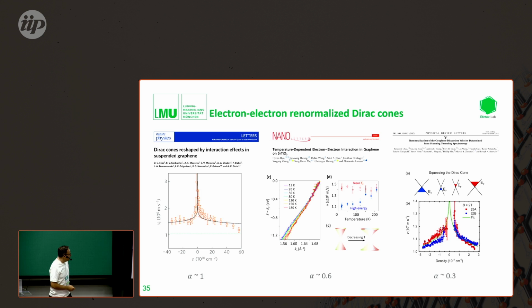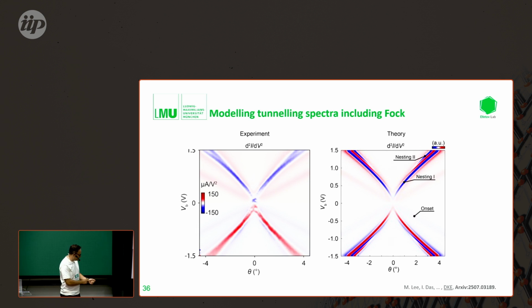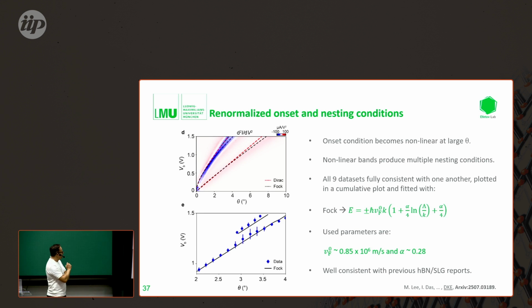So if we include this type of correction into our model, then we reproduce the same type of low energy correction here, which produces a splitting. The splitting is also exactly like the one which we observe here. So we have a smaller branch which ends, and a higher branch which takes over.